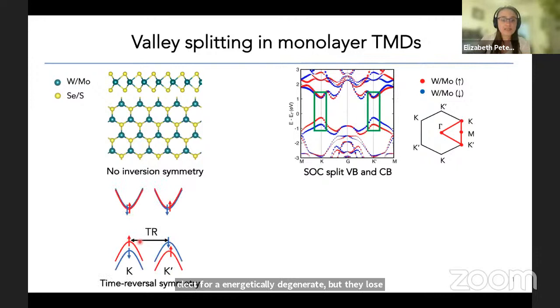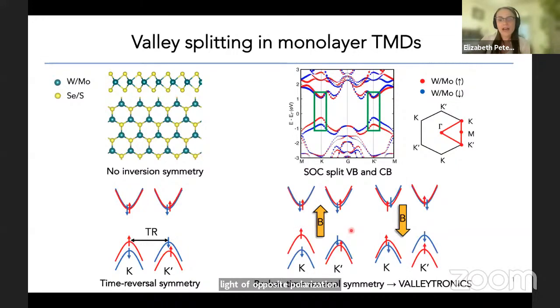They're still connected by time reversal symmetry, which gives rise to spin valley coupling, where in the spin orbit split valence band, you have up spin in the K topmost valence band and down spin in the K prime topmost valence band. One of the consequences of this is that you can selectively excite one or the other of the valleys with circularly polarized light of opposite polarizations. What I'm interested in is what happens when we break this time reversal symmetry, which allows us to isolate the band gap in one or the other of these valleys, and we can detect which valley polarization we're in using circularly polarized light. This is potentially a binary quantity that could be used in valleytronics technology for beyond Moore's law information storage technology.